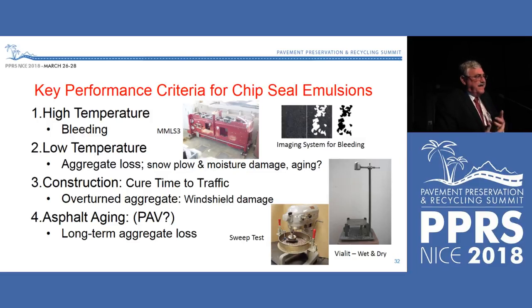And we can now try to understand what performance is before we then try to develop our test methods for the binder to simulate and give us the performance we see in these mixes. Construction time to traffic is important. The sweep test is one good thing. We can run the sweep test after however much time we allow it to cure after we apply the aggregate and get some idea. That's especially important for when we use polymer modification for heavy traffic, for chip seals.